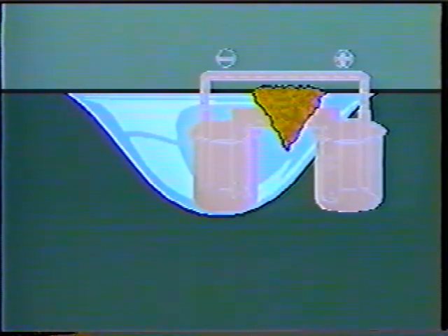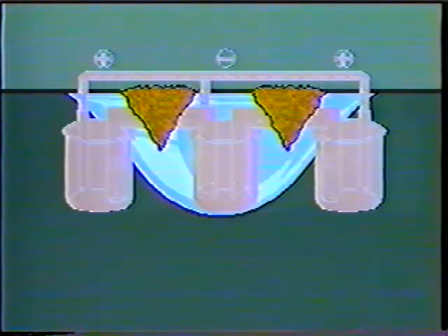This rust concentrates between the half cells, which are formed between the center and the very edge of the drop. From above, we can see that the rust concentrates in a ring between the center and the edge of the drop. So we can see that each droplet of salt solution that falls on the robot produces a tiny electrochemical cell.